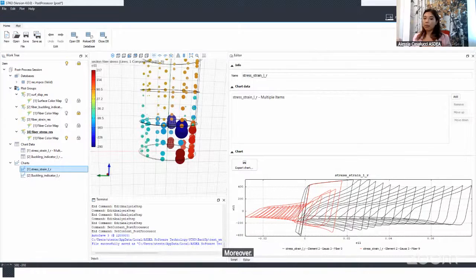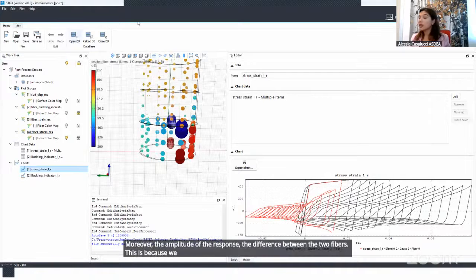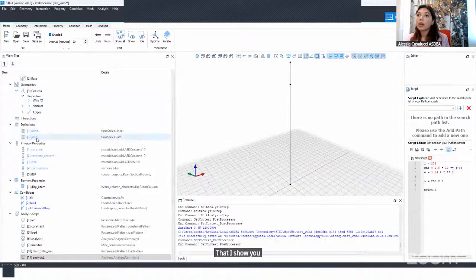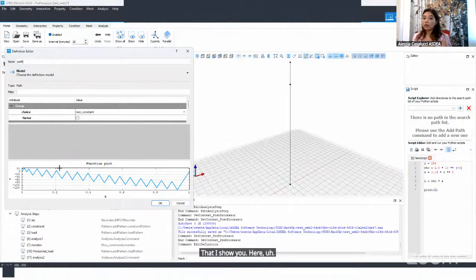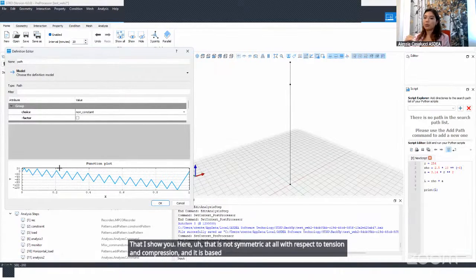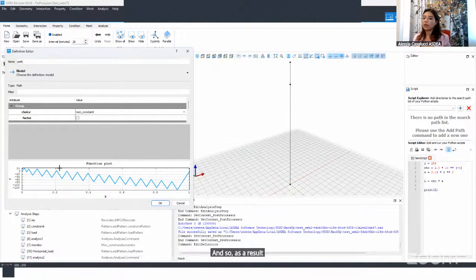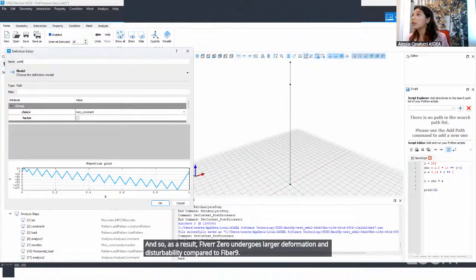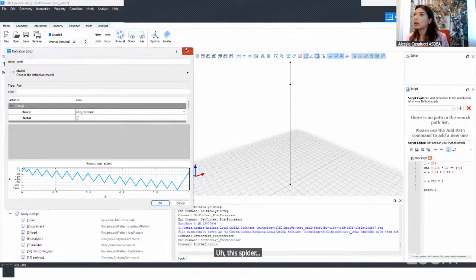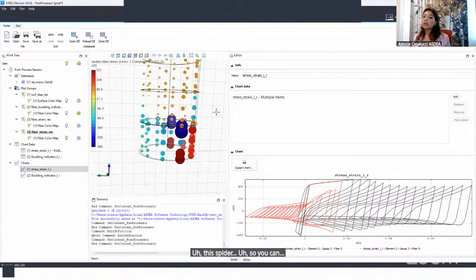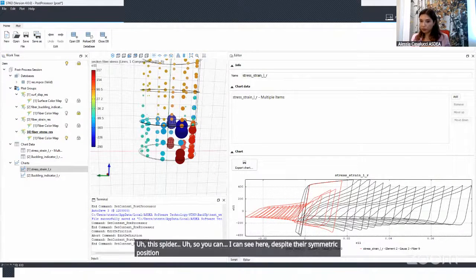Moreover, there is a difference in the amplitude of the response between the two fibers. This is because we applied a loading path, that I show you here, that is not symmetric at all with respect to tension and compression, and it is biased toward the compression, leading to more severe inelastic demands on the compressive side. As a result, fiber 0 undergoes larger deformation and instability compared to fiber 9, despite, as you can again see here, their symmetric position in the section.